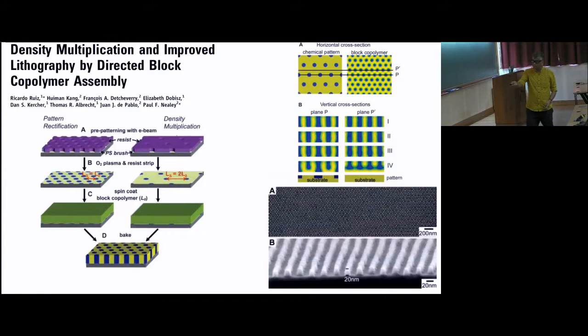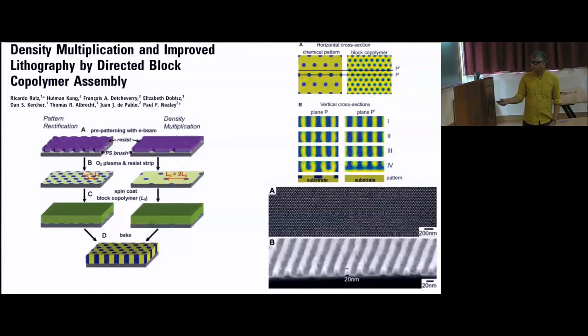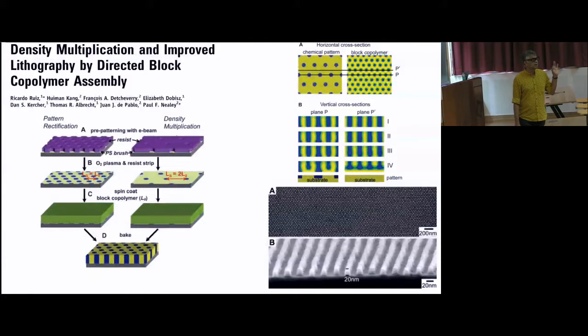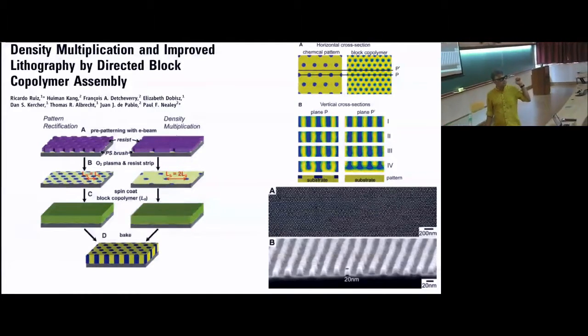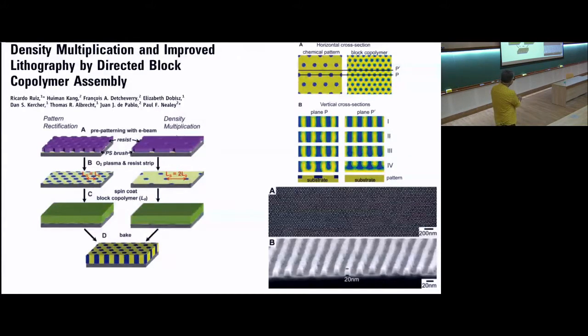You do the etching and then backfill with, for example, silicon. With a di-block like styrene and isoprene, one of them is very radiation sensitive — you can etch it out, backfill with silicon, and that's how you get this. These are cylindrical patterns, like 15-20 nanometers. The state of the art right now is six nanometer dots, and they claim that is four terabytes per square inch. These are some unbelievable technological breakthroughs happening just using the idea of self-assembly. Down here, they've made stripes using lamellae — etch away the middle layer, backfill with whatever you want. This is the state of the art for how the best hard drives are being made.